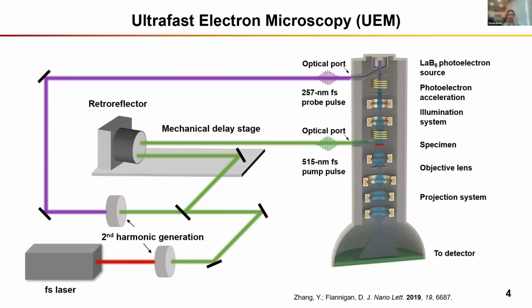I'll give a very quick overview of instrumentation. Ultrafast electron microscopy, or UEM, is a pump-probe technique. The microscope is coupled with an ultrafast pulse laser system that is split into a pump and a probe. The pump gets directed onto the specimen to induce structural dynamics, and the probe is guided onto the electron source to produce photoelectron packets for imaging. The relative arrival time of the pump and the electron packet, or what we call the delay time, is controlled with this path length difference on the mechanical delay stage. We can then acquire an image at each time point and stitch everything together in the correct time order to obtain a movie of the dynamic processes.